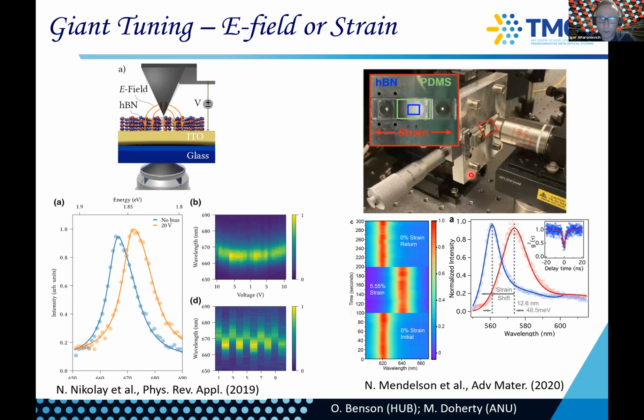And you can also strain the material. And so again, you can put it on PDMS, and you can strain, and you can see here that there is a very large strain shift, about 45 meV, a few nanometers, so about 10 nanometers, and the emission is very stable. So this is under strain and of course reversible. So it really opens up a lot of opportunities if you want to play with single photon sources for strain or for tuning, because you can now have a room temperature source that is stable, and you can transfer it onto any foreign device that you like.